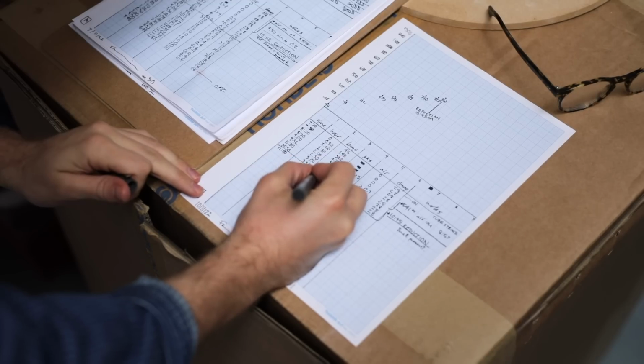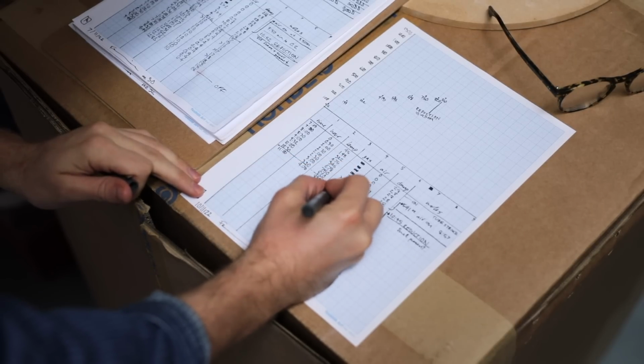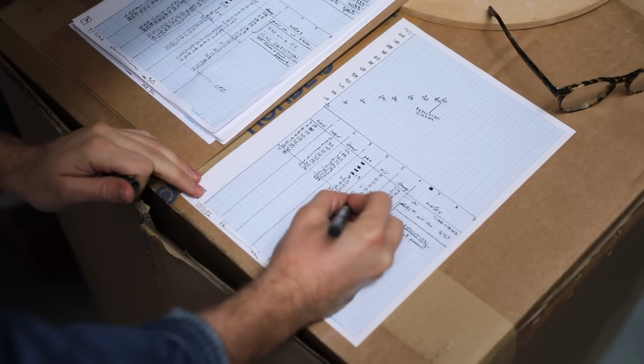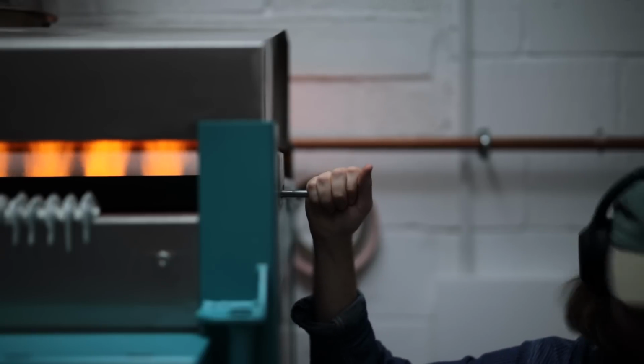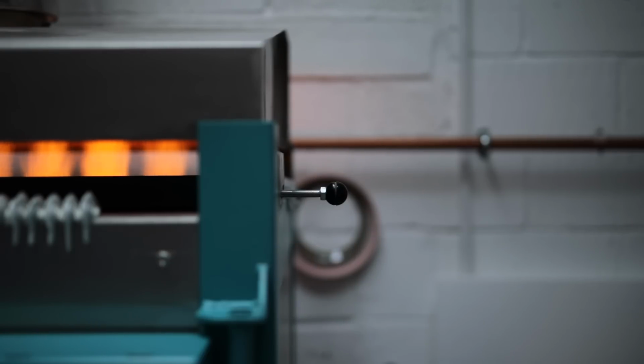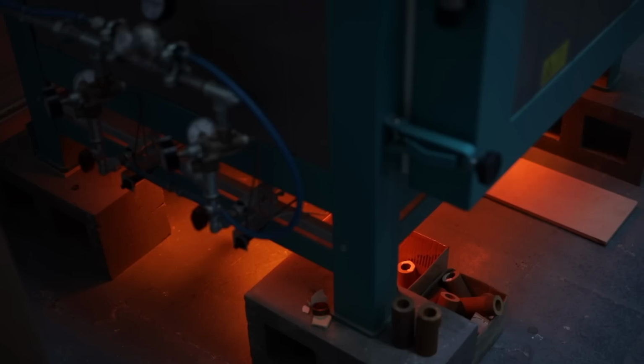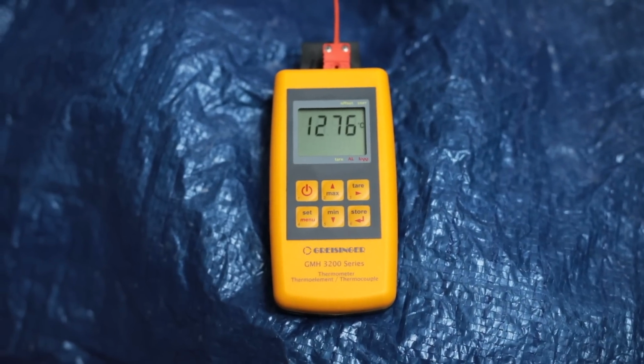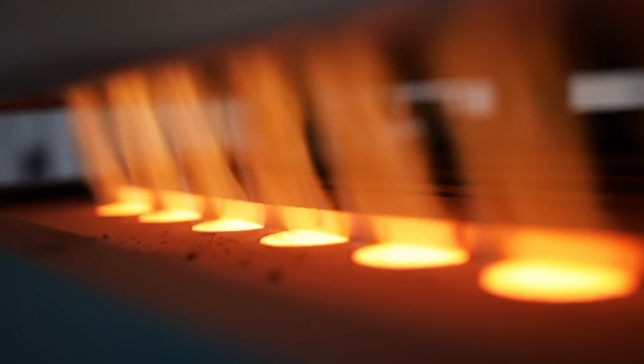It's very slow at the beginning, and I gradually increase the gas pressure and air pressure until the gas kiln reaches 860 degrees Celsius. At this point I slide the damper over the flues and dramatically increase the gas and air. This places the kiln into a state called reduction, where the fuel inside isn't burning efficiently, as there's simply not enough oxygen inside the chamber for the amount of fuel burning inside, as it's throttled and can't escape quickly enough. The burning fuel therefore finds oxygen from inside the pots and the glazes themselves, thus changing their colours and giving you qualities you can't quite achieve when using an electric kiln where oxygen is plentiful.